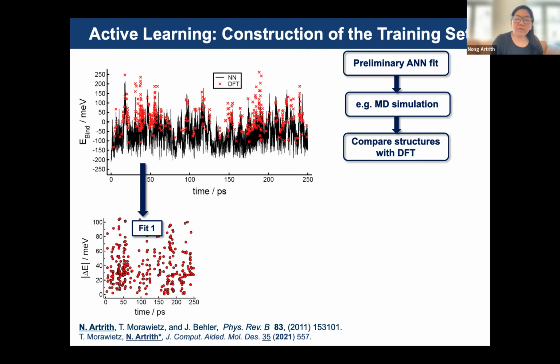In this case, we plug our NN potentials into MD simulations, and then we predict the physical properties like the binding energies of the neural network predictions compared with the binding energies of the DFT. In this case, we use the example of water. So you can see for the first training step, when you compare the DFT and the neural network, it's quite large errors that you can see.